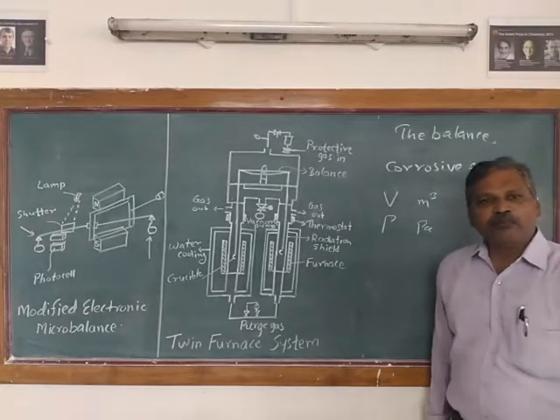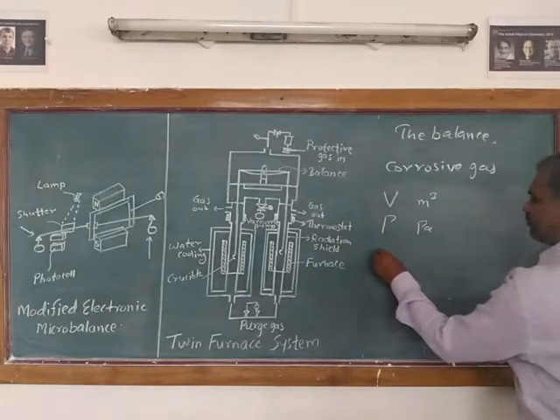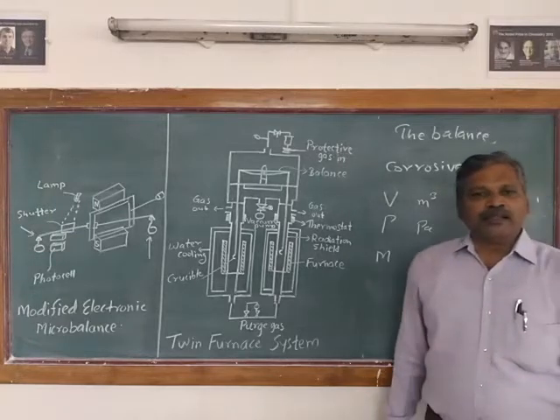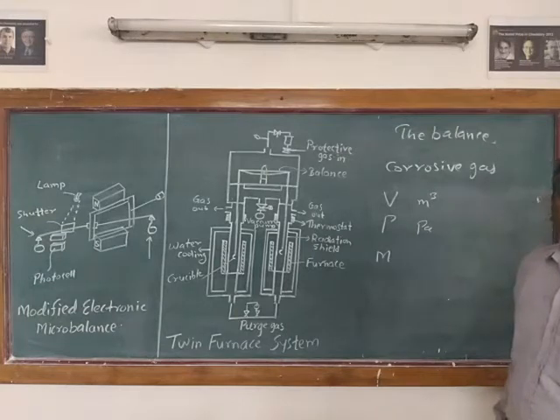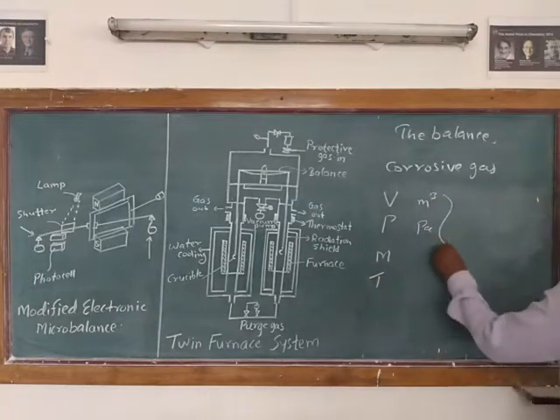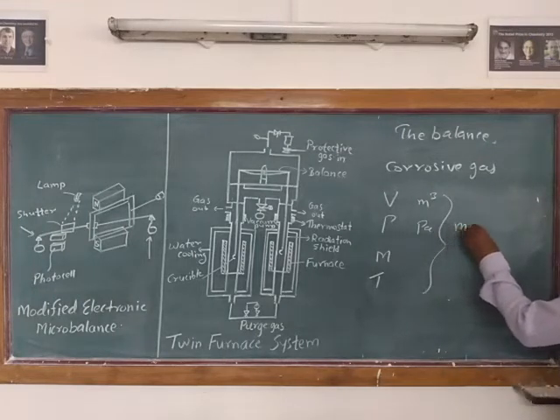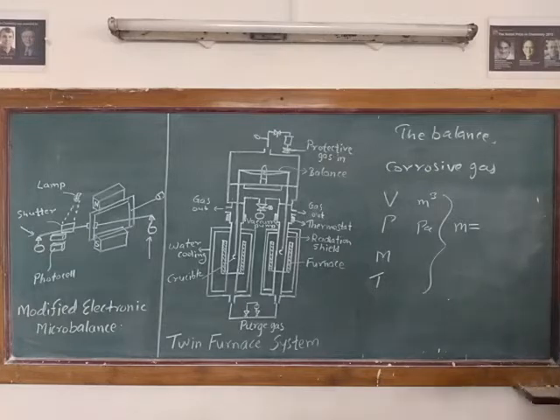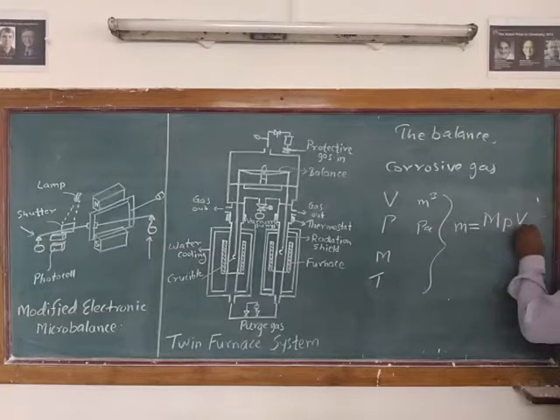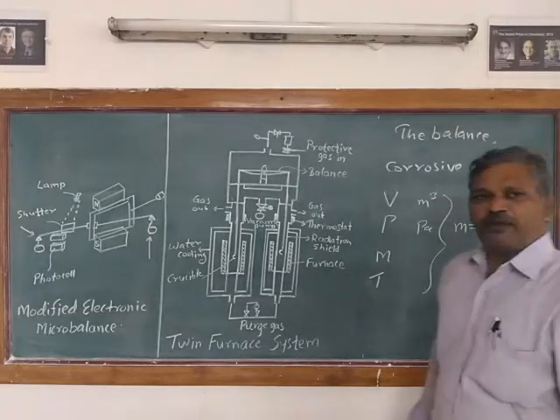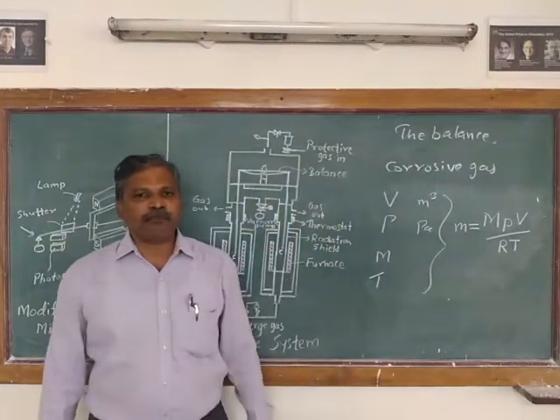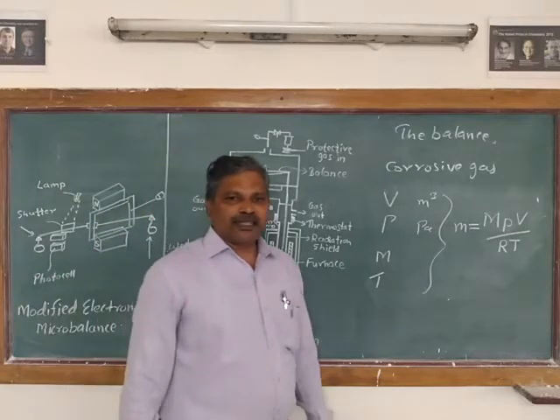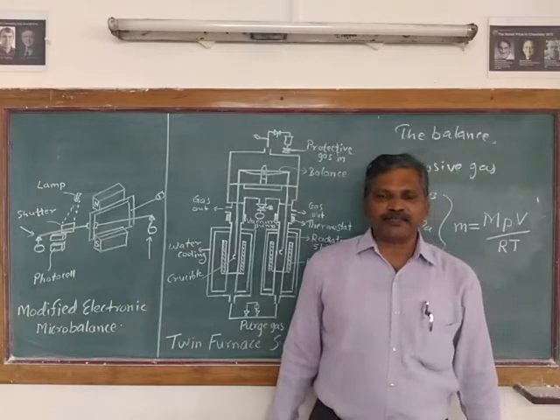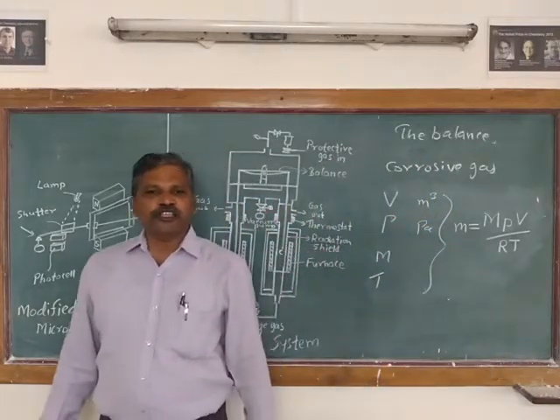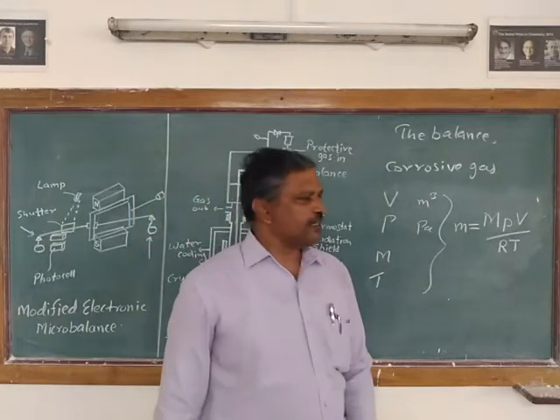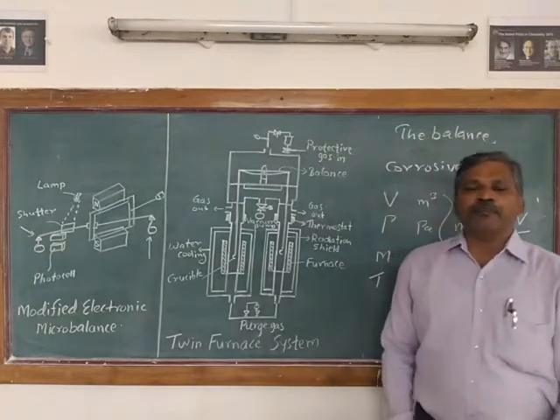then for an ideal gas having molar mass M, it will displace the volume at temperature T, and the mass displaced by that ideal gas will be MPV divided by RT. So in this way we can get how much upthrust is applied on the sample. As the sample is heated, the density of the gas decreases, but the density of the solid hardly changes. Therefore, the upthrust will decrease and the sample will apparently gain some measured mass.